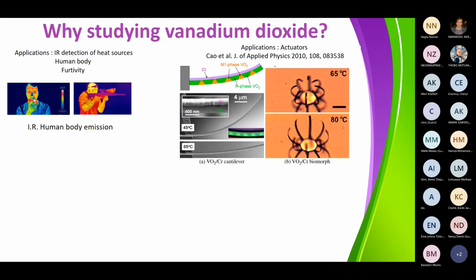Another application of vanadium dioxide is actuators. You can use this because of the difference between, for instance, chromium in this case and vanadium dioxide. They don't have the same thermal expansion. And when vanadium dioxide goes through the transition, you can use this as actuators, and you can very easily use this in many cycles, like more than 10,000 cycles. And that's a very interesting story.